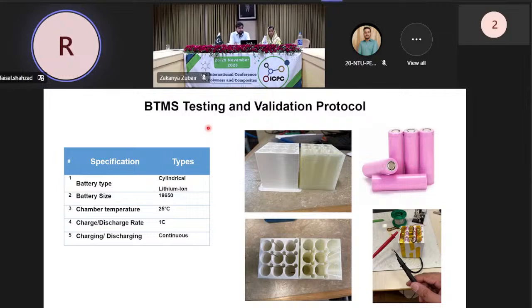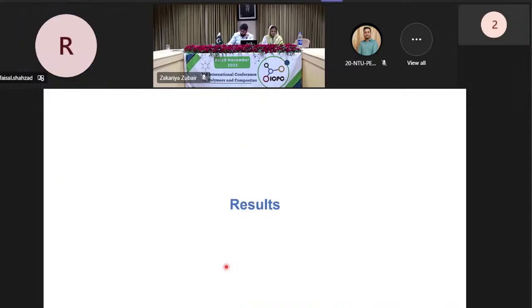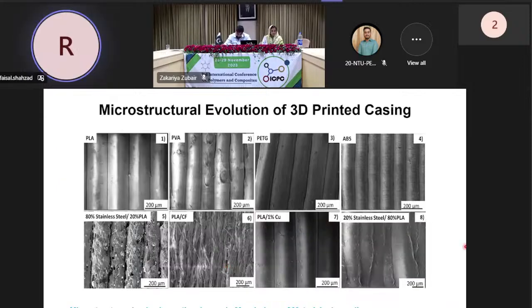So, battery thermal testing and validation. Mostly the EV industry in the UK uses cylindrical batteries. So for lithium-ion batteries, we have tested our material on an 18650 cylindrical battery, and the chamber temperature is fixed at 25 Celsius. The charging rate is 1C, so the battery charges and discharges at 1C. It's continuous charging because we want to know the impact of continuous charging and discharging of the battery, and how the material behaves with the temperature of the batteries. So you can see we have a printed battery pack, and we made this whole setup at Northumbria University. I will quickly go through the results.